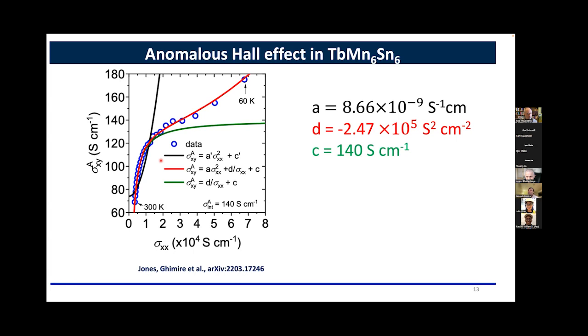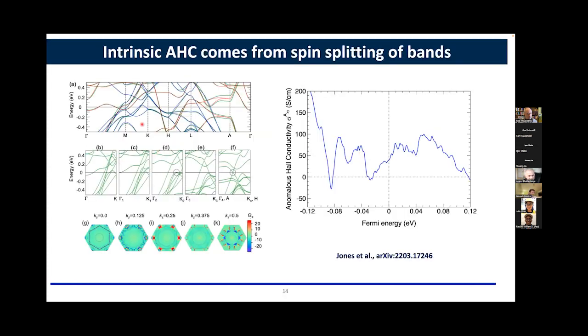But I'll show you another, because we were working on these different 166 compounds, and we're making other compounds. I'll show you that now we believe that this 1 over sigma XX may be coming from the fluctuations. And just to touch base upon this intrinsic part, what we have shown very clearly by doing a band structure calculation, which matches pretty well with the experiment, is that we don't need the topological phenomena for this. Just the spin splitting at different kz locations gives the Berry curvature, and that Berry curvature is good enough to give rise to the anomalous Hall conductivity in this material.